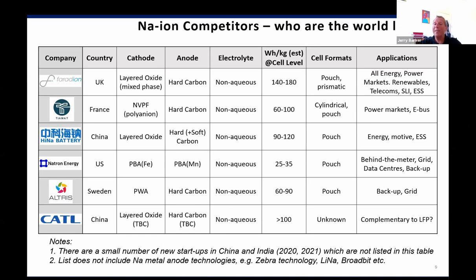And their cathode, as far as we can tell, based on the IP again, it looks like it's going to be layered oxide. That has to be confirmed. We're pretty sure the anode is going to be hard carbon. Again, that has to be confirmed. And it looks from the initial data that we're taking from the most recent filings that the specific energy will be something over 100 watt-hours per kilogram and clearly improving.